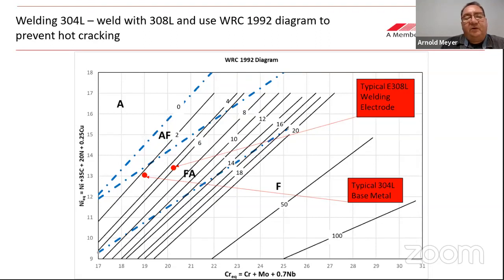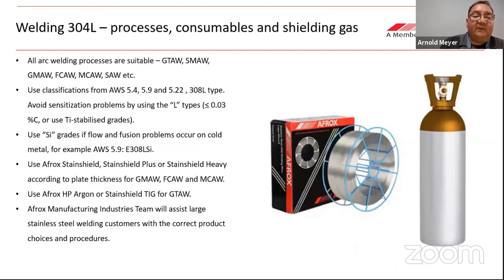If you weld with 308L, you can see that with dilution, it will move it a little bit closer to the 308L dot. And if you have multi-layer welds and you keep on welding with 308L, you will be safely inside that region. We will look at the same diagram for 316L as well.